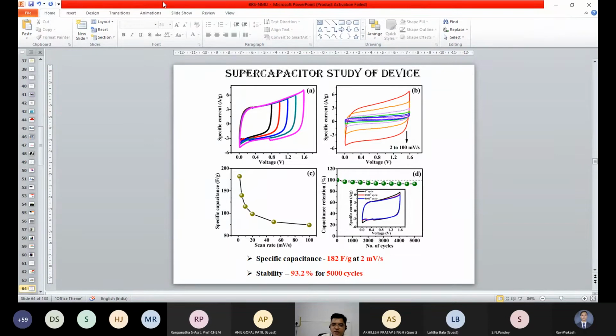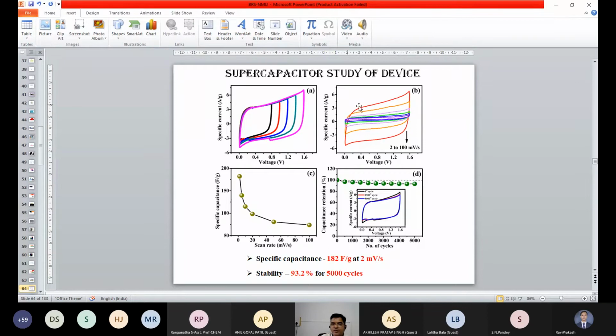And we have calculated the specific capacitance, which is about 182 farad per gram at 2 millivolt per second. And also, the solid state device that was formed shows a cycle stability of about 93% for 5,000 cycles, and that is the beauty of vanadium sulfide.